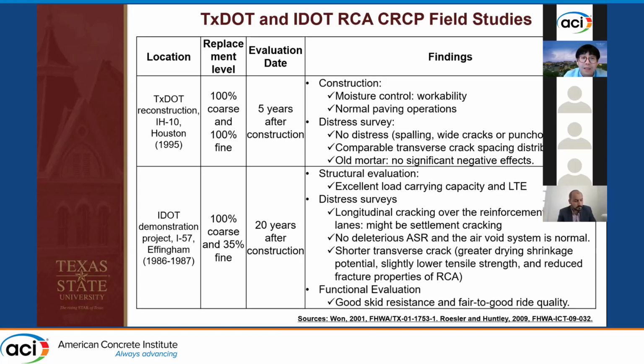site, and they had a report. The major findings were that the contractors noticed that the moisture control of the RCA stockpile was very crucial, because if we do not control the moisture content of the RCA, then the consistency of the RCA concrete will be very bad. They were able to use normal paving operations to construct those RCA concrete pavements. And for the distress survey, no distresses were found. The transverse cracking spacing distribution was comparable to the control,